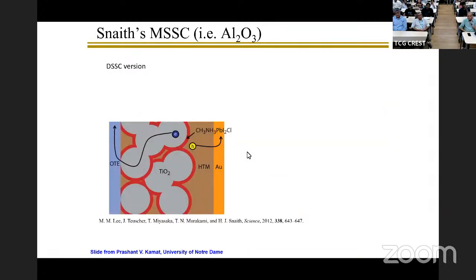Not only that, another very interesting thing was discovered very early on. Originally one thought that this technology is like the dye-sensitized solar cell. What is a dye-sensitized solar cell? It's very simple. The photon is absorbed by the dye. Dye implies something very colored. The fact that something is colored is because it absorbs a part of the visible solar spectrum very efficiently. And having absorbed, it creates an electron and hole, but the dye is normally not a very good conductor of the electron and hole. So what one did was to put titanium dioxide particles that are coated with the dye that created the electron and hole. The electron jumped into the TiO2 and got transferred to one terminal, and they put some other hole extracting material on the other side. The hole went to the other electrode, and that drove the electricity outside. And that's how one thought that this material also works.